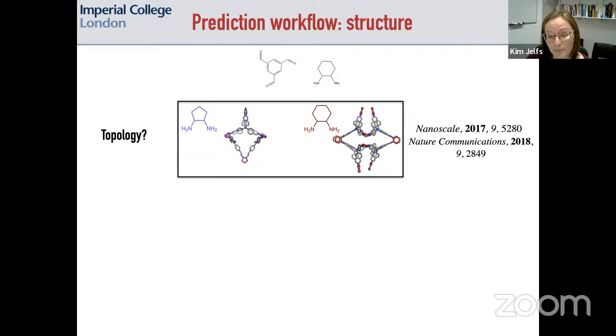So very different outcome, as well as a different topology, it's a completely different shape. But worse than that, its properties are completely different. In fact, that molecule ends up being completely non-porous, and also amorphous, and that's really unfortunate because the experimental postdoc that spent a year and a half synthesizing that was hoping to get a really porous system, and it in fact wasn't. And this showed us the value in doing modeling in advance that would tell you which topology you're going to get and also its properties, because you don't want to spend a year and a half going to the effort of doing all the organic synthesis and characterization necessary here to find that it's not porous if that was your aim.